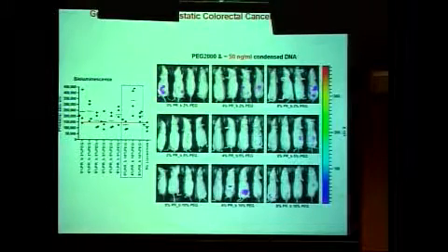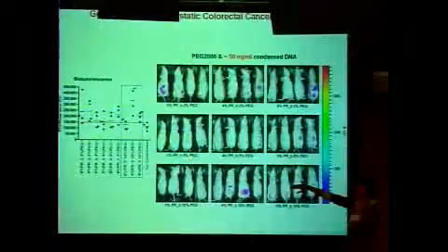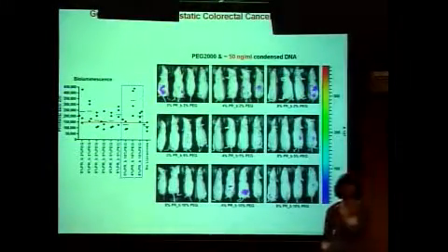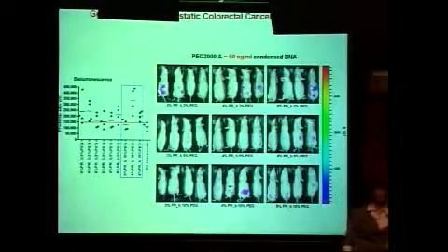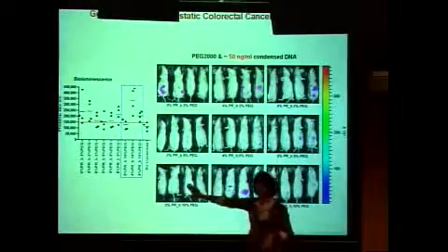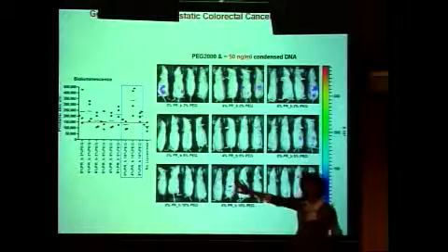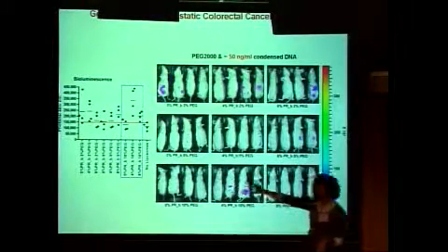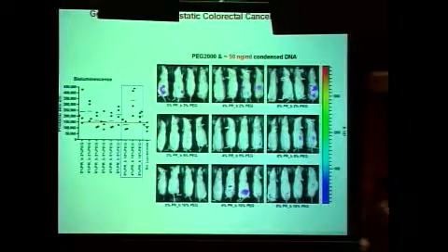And for that, we decided to evaluate 9 different designs. The first row shows you nanoparticles that have a little bit of the polymer, but not enough. The second one, we increased that from 2% polymer to 5%. And the third one, we have a lot of the polymer, a lot of the repulsion, 10% of the PEG. The first column shows no targeting, no peptide. Second one, 4% of my peptide. And then finally, 8% of the peptide.